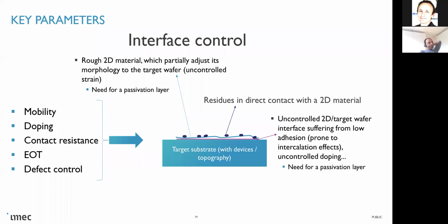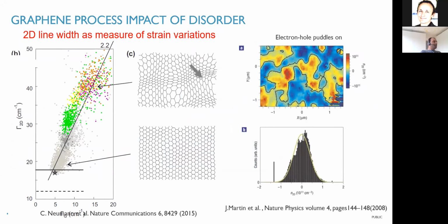Because towards mobility, towards VT shift, towards contact resistance, all these parameters have an enormous importance, and that's why I would like to address this a little bit. So, for graphene, it's common that you can only have really high performing graphene if you try to avoid all these strain variations and so on. And this is reflected in the full width half maximum of the 2D peak. We have a relatively good understanding that if we can control and lower the full width half max of the 2D peak during our manipulation, we can go to a high performant material.